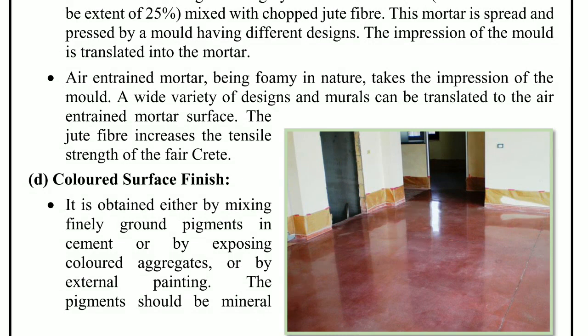The fair-crete mortar is mixed with chopped jute fiber. This mortar is spread and placed by a mold having different designs, and the impression of the mold is translated into the mortar. The foaming nature of the mortar takes the impression of the mold, allowing a wide variety of designs to be translated to the air-entrained mortar surface. Jute fibers increase the tensile strength of the fair-crete.